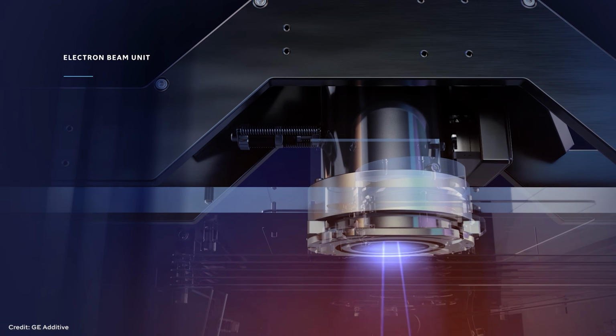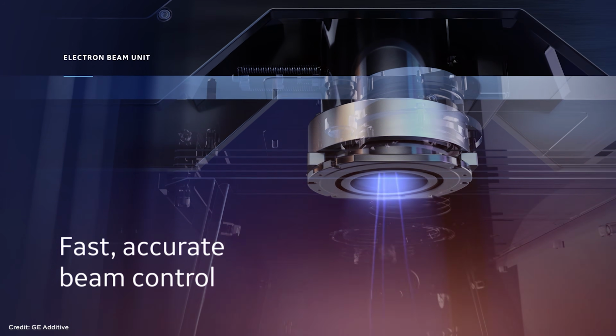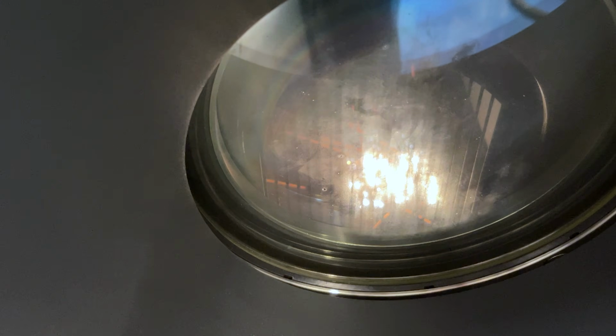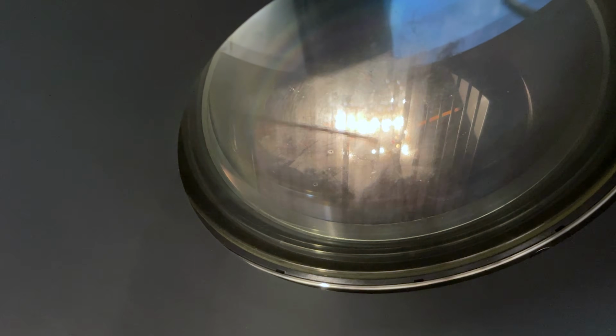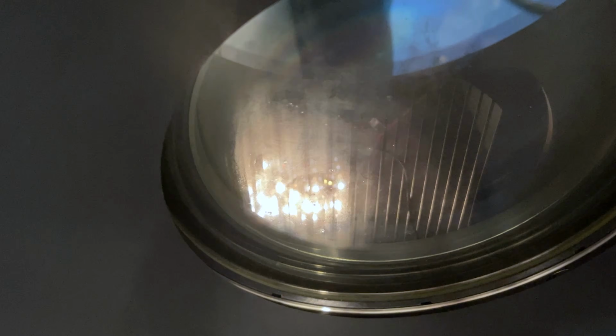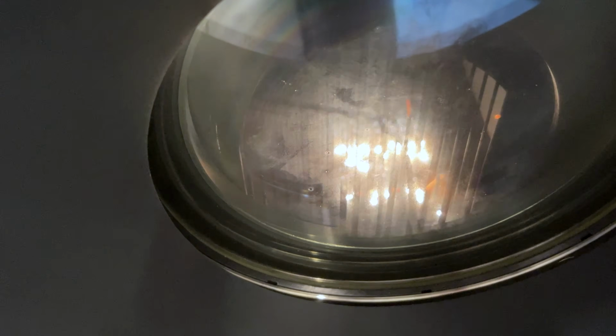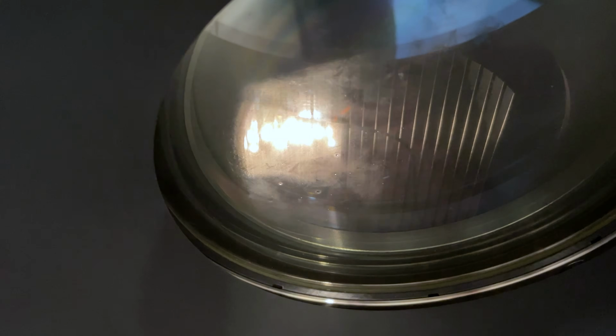And lastly, the other main point is the ability to manipulate the electron beam in a manner that, to your eye, it looks like there can be tens or 20s of melt pools or beams within the chamber simultaneously when it's still only one electron beam. And this helps us control the stresses that develop while printing parts. It's these three factors together that make electron beam melting a unique technology; you can't get them all in other technologies. So electron beam melting with tungsten potentially leads to better material properties along with more complex geometries.